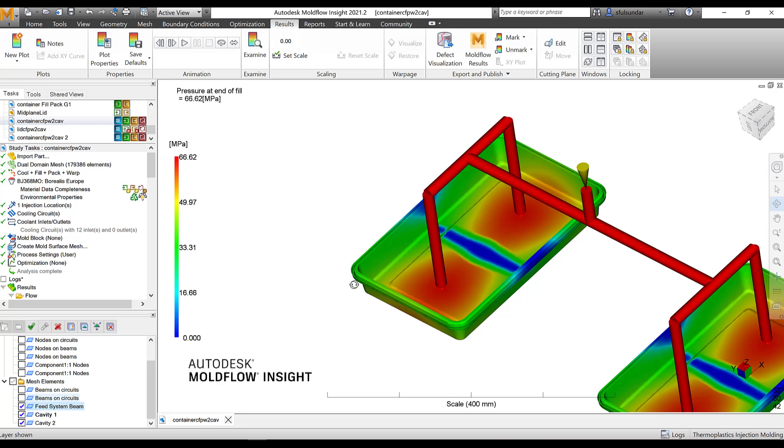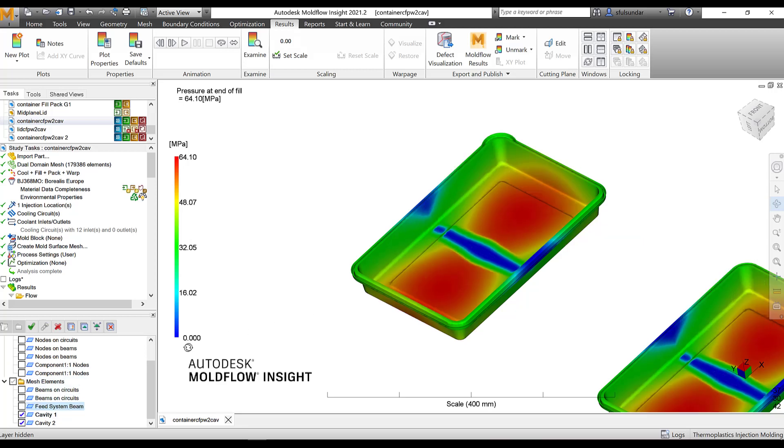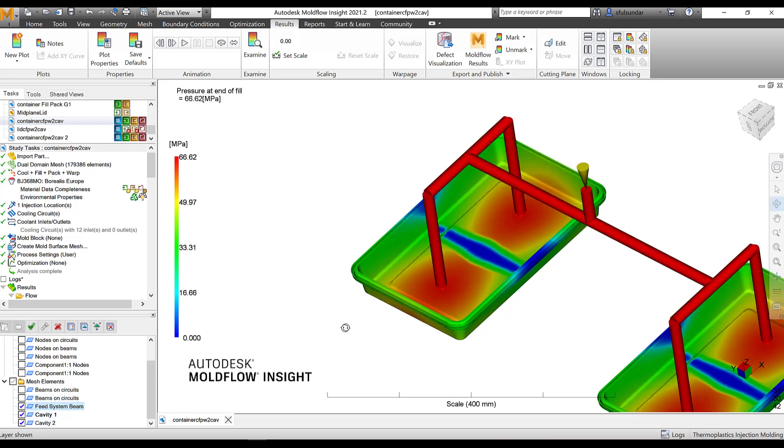Try to keep it not more than 75 to 80% of the machine capacity. Usually, in Moldflow, we follow the thumb rule is that the pressure in the part should not exceed more than 80 MPa and with the feed system, it should not exceed more than 100 MPa also, but if the part is very thin involved and probably you need that high pressure to be maintained. Try to see that it doesn't exceed 75 to 80 MPa.